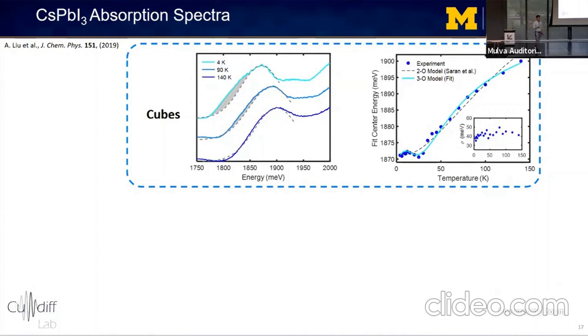So here you can see absorption spectra of the perovskite nanocubes as a function of temperature, where we see a distinct peak corresponding to the lowest exciton transition. And we can fit this peak to pull out a center energy and line width as a function of temperature. And if we look at the dependence of the center energy on temperature, we find that the exciton resonance blue shifts with increasing temperature due to exciton phonon coupling.